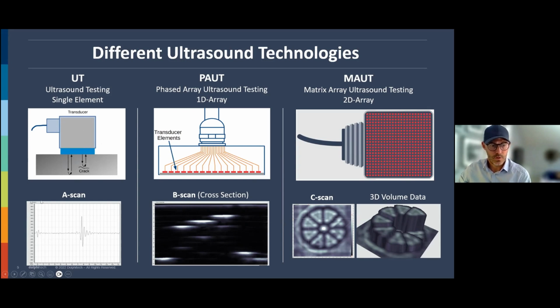So that results in what we call an A scan. So you get a small echo here, a penetration echo in the beginning, and then here you see a larger echo in the back wall. So this is the pulse of that acoustic wave that you sent out. If you hit the back wall here, then maybe your A scan is located here. But if you hit the crack, then the A scan comes earlier. And then you can see that you have some sort of object that is preventing the sound to travel through your medium. And that's what you use to inspect. And for example, to inspect on an aircraft, you need 3,000 hours of training to be able to use this kind of technology. And it's kind of old technology. It's still very much used today, but it requires more expertise to use it.